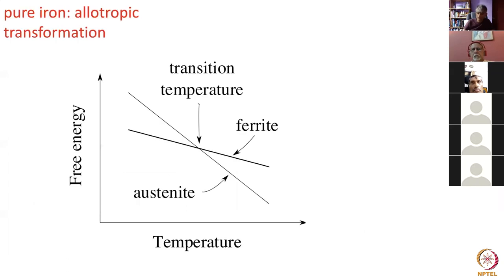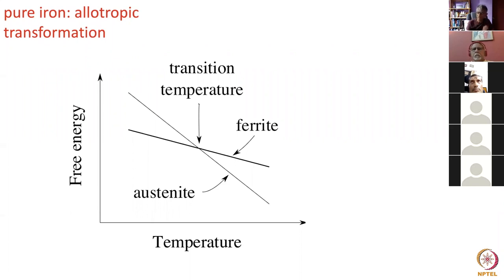Now if you are dealing with a pure substance, for example pure iron, and it can adopt different crystal structures at different temperatures, then the free energy is simply a function of temperature or pressure. We can plot curves showing the free energy of the body-centered cubic form of iron and the face-centered cubic (cubic close-packed) form of iron, and where they intersect, these two phases are in equilibrium because they have exactly the same free energy. It's easy to define equilibrium for a case where there is no composition change.